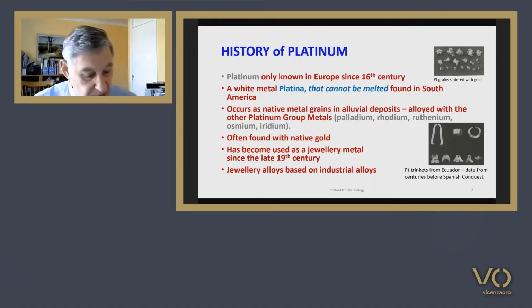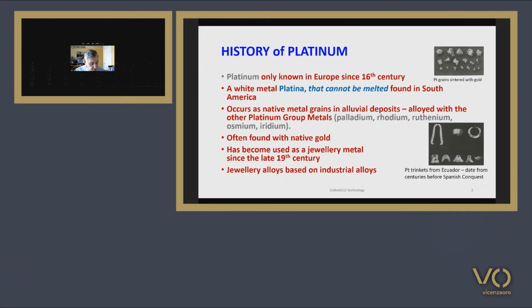Platinum has only been known to Europe since the 16th century, with rumours of the existence of a white metal, platina, in Central and South America. Alloyed with the other 5 platinum group metals: palladium, rhodium, ruthenium, osmium, and iridium. And these were exploited by the pre-Columbian Indians of Ecuador and Colombia in northwest South America. Analysis of ancient trinkets indicates that iron and copper were also present as impurities.